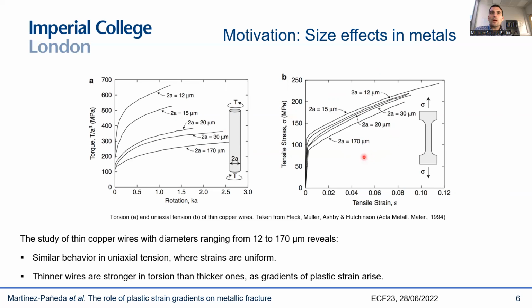And as you can see in uniaxial tension, those strain curves that they obtained were roughly insensitive to the diameter of the wire. You can see that more or less all the curves fall on top of each other independently of the diameter of the wire. However, in torsion, when we go to these normalized stress strain curves, you can see there is a very significant size effect, with thinner wires being much stronger than thicker wires. You can see that the flow stress for thinner wires could be 3-4 times the one of thicker wires.